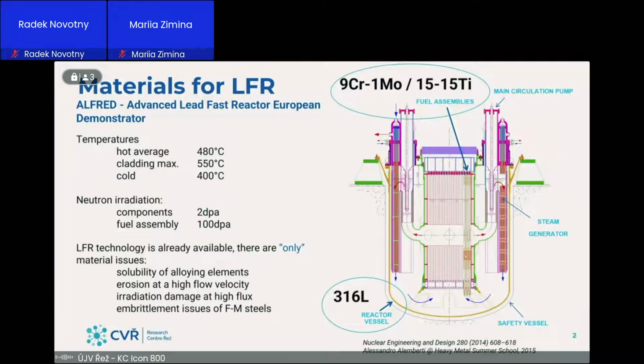There is a core, and I will talk today mainly about 316L, that is supposed to be a reactor vessel, and 15-15 titanium or 9% chromium steels, ferritic martensitic, as candidates for fuel cladding. This cladding has a wall thickness of 0.4 millimeters, so its corrosion is very critical.